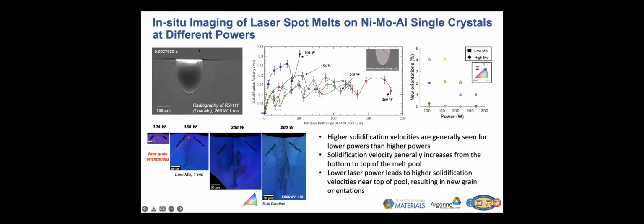These are without a powder layer. These were done on nickel moly aluminum single crystals that were obtained from Teresa Pollock's group at UCSB, provided to us in the form of high pedigree single crystal castings. The benefit of this is that we were able to strategically cut out specific crystallographic orientations for these nicely controlled experiments. Shown over here is an example of a typical spot melt in one of these single crystal samples.